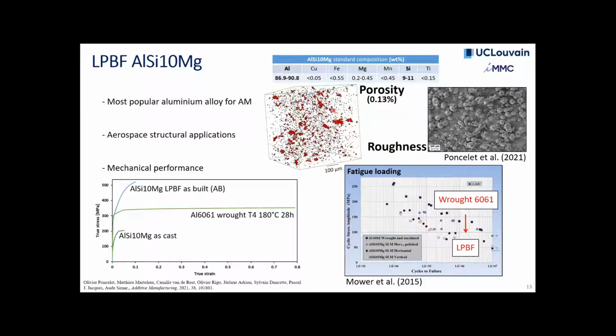And so if you look here, actually, this is a tomography image. I'm going to show you a bit more of these later on, but we have here about 0.13%, which isn't much, as you would tend to say, but you already have these really huge porosities here that are lack of fusion porosities. So this is on an EOS machine, really optimized parameters. So you can really say that this is an optimized condition, and we're definitely not into something that is unusual.